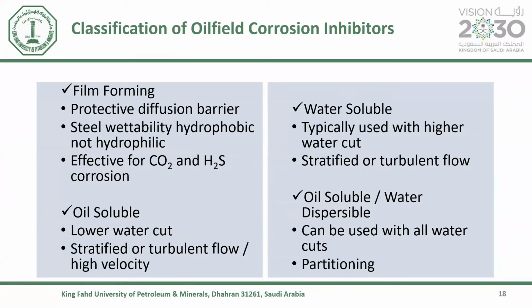Oil soluble, they are normally used for lower water cut and very effective for stratified or turbulent flow regime. For water soluble, this is normally used when you have higher water cut and can be effective for stratified or turbulent flow regime. Then when you have oil soluble water dispersible, this can be used with all water cuts, and this is mainly a kind of inhibitor that can partition between the oil and water phase.